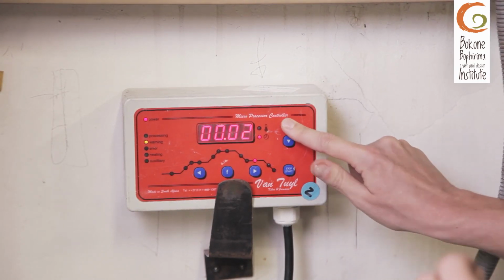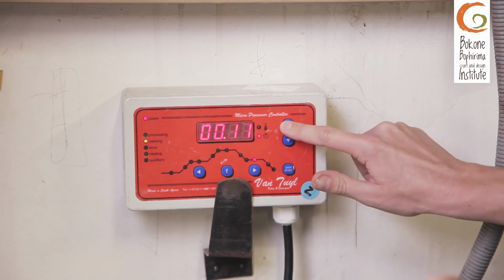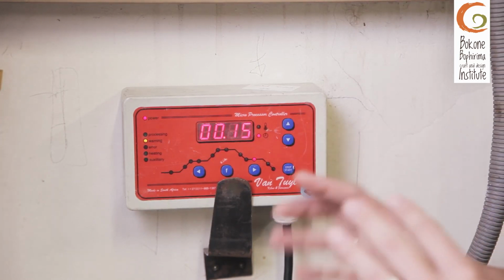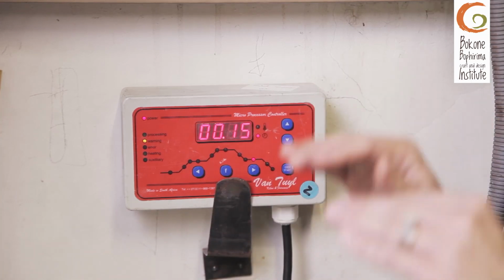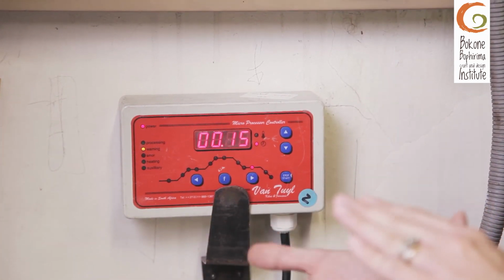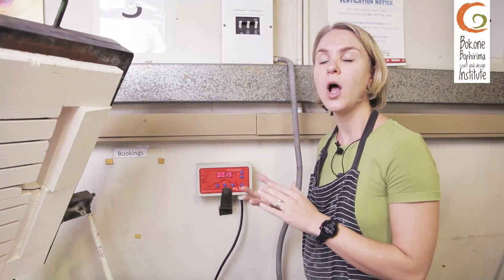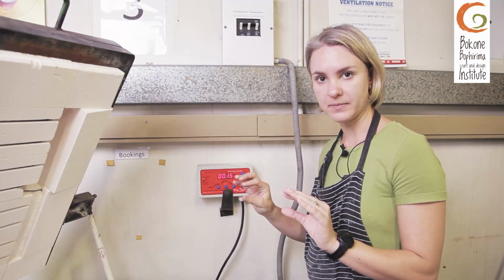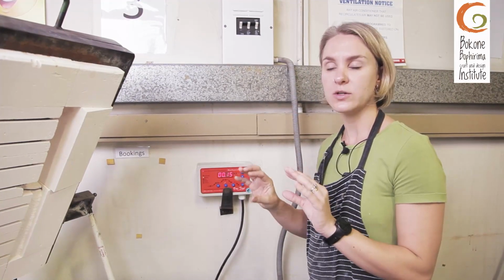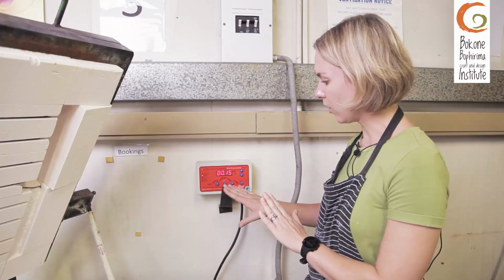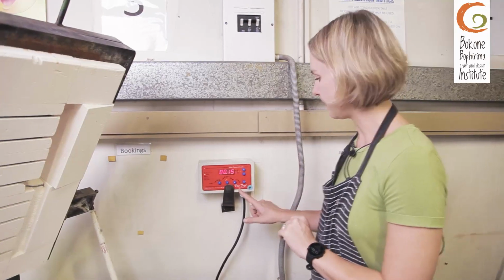If my glass was thicker, then I would hold it for longer, because it is important that the glass is evenly heated before annealing it down. You don't want the middle part of the glass, which normally takes longer to get to the desired temperature you have. So it's important to anneal and hold it there before bringing it down.